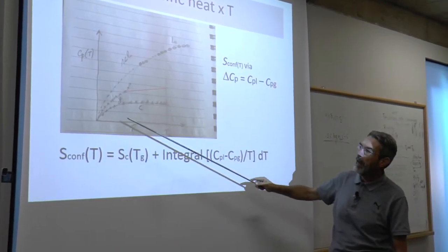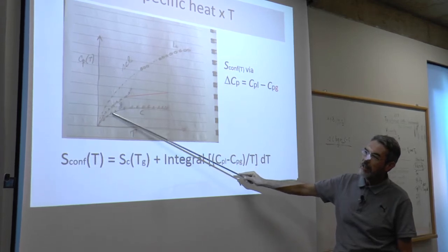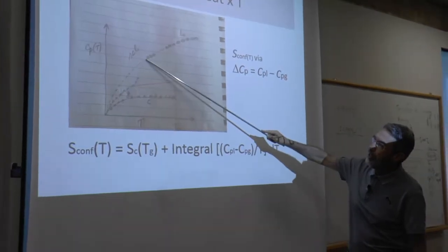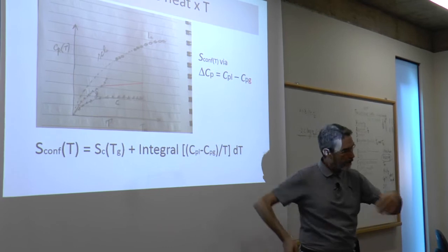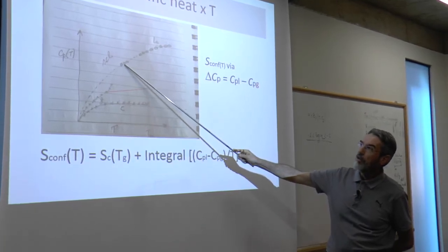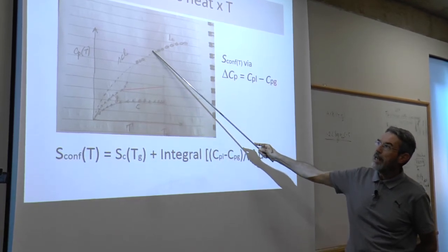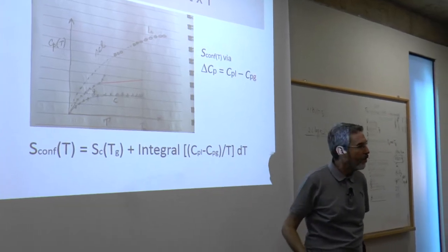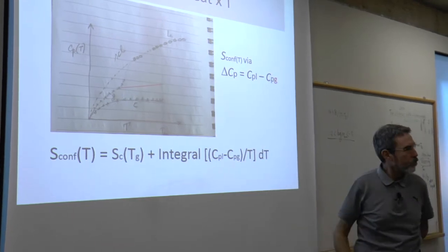isochemical crystalline material. Then you have the specific heat of the glass. See the data points here? The specific heat of the glass is a little bit higher than the specific heat of the crystal because of the configurational contribution. It has a vibrational and a configurational contribution, and then you go to Tg, there is a jump, because then you move from a frozen liquid to a supercooled liquid. There is a jump, more freedom in these molecules. And then maybe you even measure, the circles here mean measurement points, a little bit above Tg. Again, you normally enter a region where crystallization happens, so you can no longer measure the specific heat, but you can measure in the glass, through the glass transition, and a little bit here in the supercooled liquid.